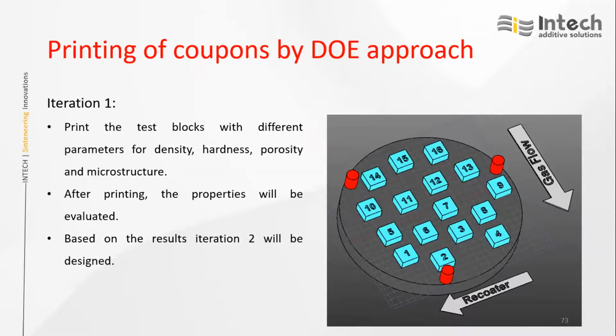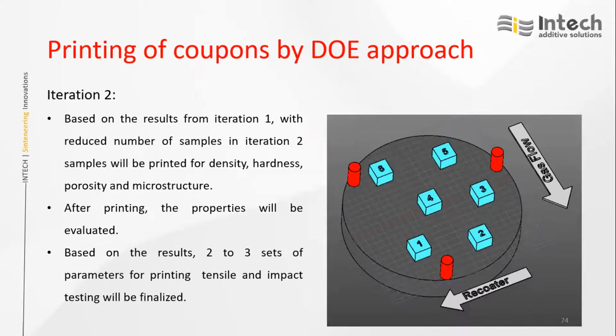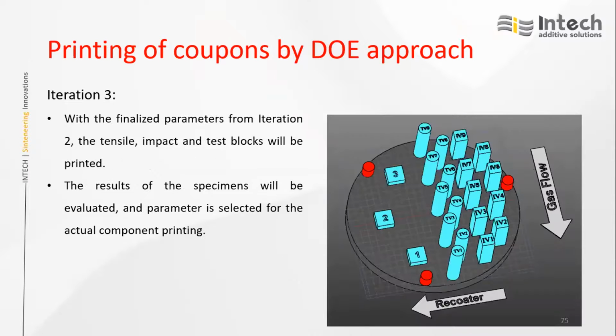Few parameters are good, so taking that as reference, we split for DOE 2 with a lesser number of samples. In this process, if we optimize it, again we need to check for density, hardness, porosity, and microstructure. If it is satisfactory, then we pick the best parameters from that and print for tensile and impact testing.